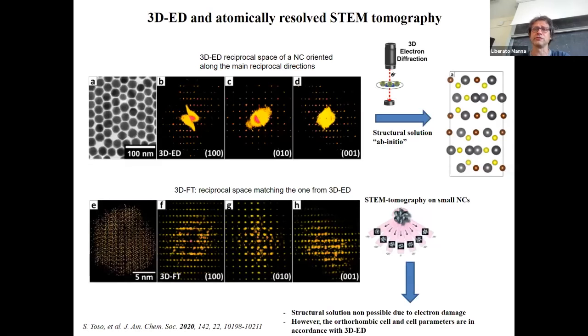And to solve the crystal structure of these materials, we had to combine 3D electron diffraction from single nanocrystals. Also, with the help of the group of Sara Bals, we did scanning transmission electron microscopy on single nanocrystals, and we did tomography, and we reconstructed the whole reciprocal lattice. The nanocrystal was damaged during this acquisition, but we were still able to recover the lattice parameters and the size of the cell, which matched very nicely with that from 3D electron diffraction. But anyway, without going into detail, we were able to figure out the structure of these nanocrystals.